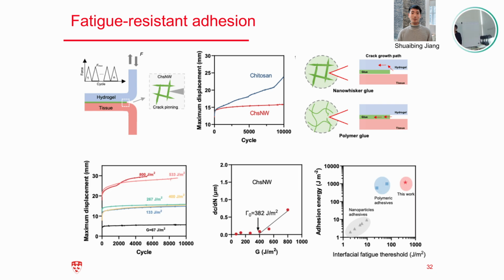To further validate that this phenomenon, which we call fatigue resistance, is real, we have tested this crack propagation under different kinds of loading, from 67 to 800. From this result, we can calculate how fast the crack propagates under different loading. As you can see here, when you apply a larger load, you have some level of crack propagation. But when the loading is slightly lower, you see the crack is pinned, the crack is stopped, it doesn't propagate. And the value we got is called the fatigue threshold, which is 382 joule per meter square.